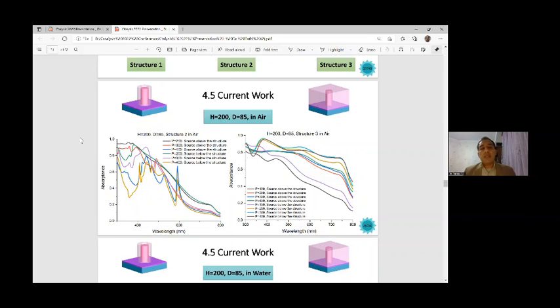For analysis, we have used the finite difference time domain simulation method in obtaining the results. In structure 2, on the left, you can see that both in water and in air, the amount of absorption does not matter whether the light source is above or below the structure. Only in the range of 300 to 400 nanometers, when the source is above, is the absorption better.